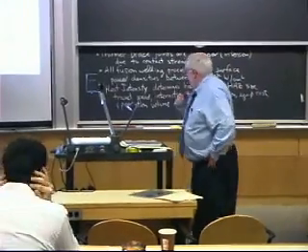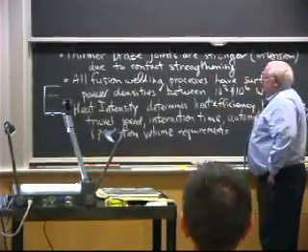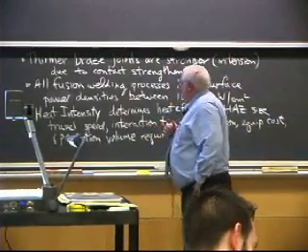Okay, last time we had talked about, we just finished up on braze joints and pointed out there's contact strengthening. So the thinner the braze joint, the stronger, although you really got to get down to about 1/1000th of an inch thick to start seeing much of an effect.